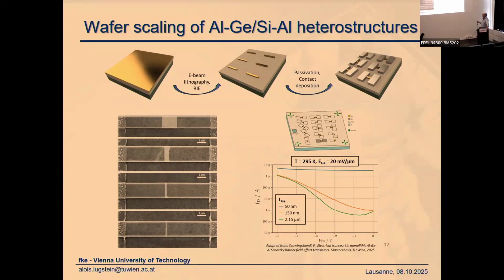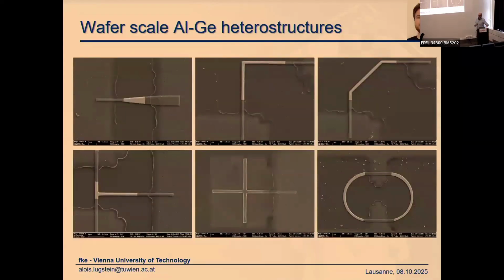Also here we can make an ultra-scaled device close to the mean free path of the electrons, which seems to behave as a ballistic device. So now we are no longer restricted to these rod-like one-dimensional structures. We can make whatever we want. We can make tapered structures, kink structures, tripods, bent structures, and even these van der Pauw structures.